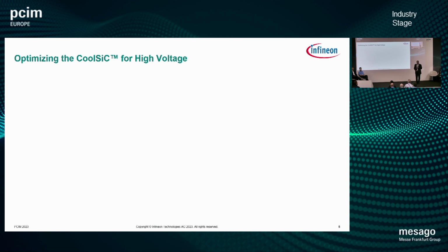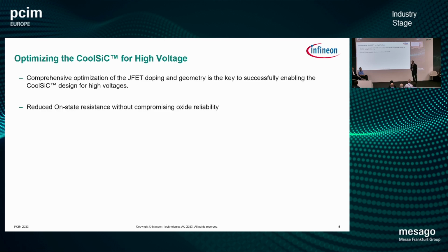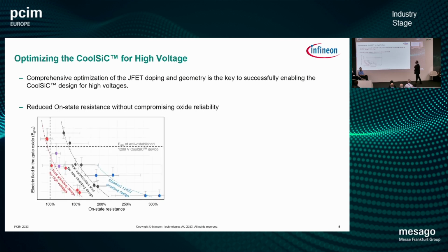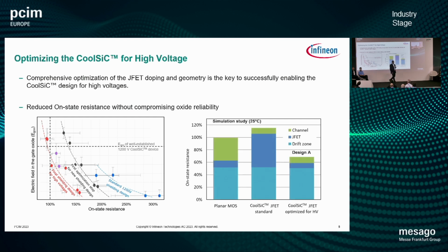What I would like to focus on, also as part of our publication, is that we took the existing optimized 1.2 kV silicon carbide MOSFET, but we clearly see that this is not enough and needs optimization to go to higher voltage. The impact is clearly in the JFET structure, where we want to optimize the JFET doping and the geometry, and adapt it to high voltage, so that we are able to have the same gate oxide field strength. In this graph, we see a higher RDS(on) if we end up with the same JFET structure.